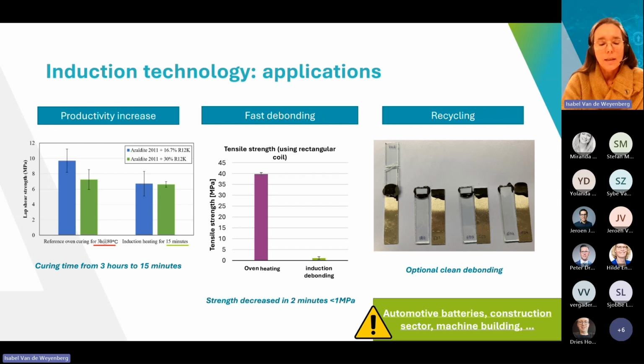Like I said, we can enable fast curing with this induction technology, which is of course a really nice extra. So it's not only about debonding, but also about fast bonding. What you see here on this graph, the vertical axis is a measure of the lap shear strength, which is also indicating the curing degree. And the blue bars are a commercial adhesive mixed with about 15% of these electromagnetic particles, ferromagnetic particles, and the green bars are mixed with 30% particles.